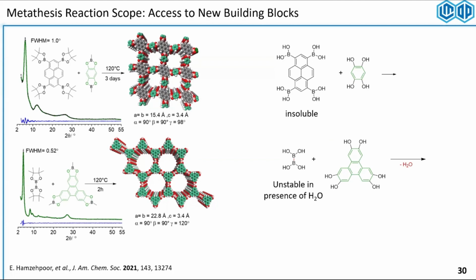So even in the most anhydrous conditions that we could work with, as soon as the reaction occurs with this catechol, essentially the boron gets connected to these 2 oxygens, there's going to be 2 water molecules released, and this release of water molecules would break the B-O bond. But using our methodology with the B pins, now this problem was solved. There was no water releasing. It was the methyl pinacolate ester releasing into the reaction, which was inert to these conditions.